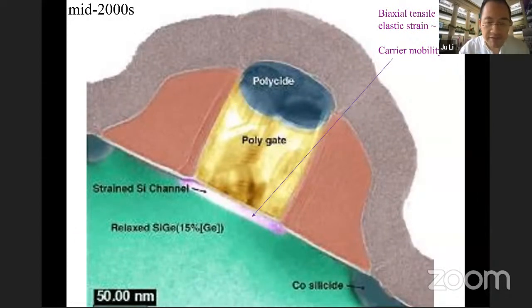And already this effect was taken advantage of by the semiconductor industry in so-called strained silicon technology. What you see here on the substrate is a silicon germanium alloy, and on top of it is epitaxially deposited silicon, which is under a tensile strain of 1% in both directions. The reason they do this is because it has been shown to improve the velocity of electrons by a factor of 2. So you get faster transistors, and this is actually one of the main reasons for the delay of the breakdown of Moore's law.